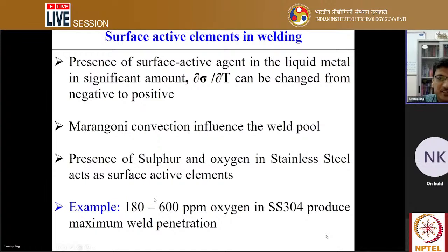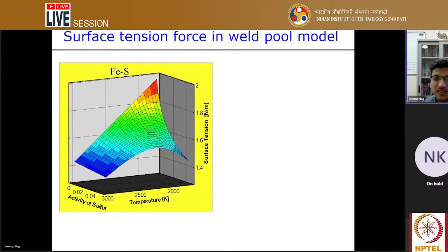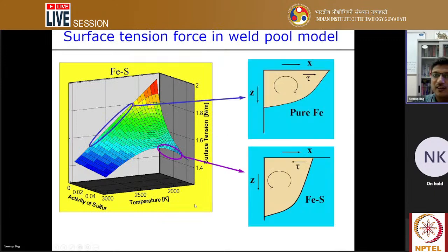Here you can see one example: 180 to 600 ppm oxygen in SS304 produces the maximum weld penetration. That means in that case, between 180 to 600 ppm, oxygen in SS304 acts as a surface active element, and it tries to maximize the depth of penetration and minimize the width. So we can take advantage of the presence of the surface active elements to achieve the full depth of penetration in the welding process, even for gas tungsten arc welding.